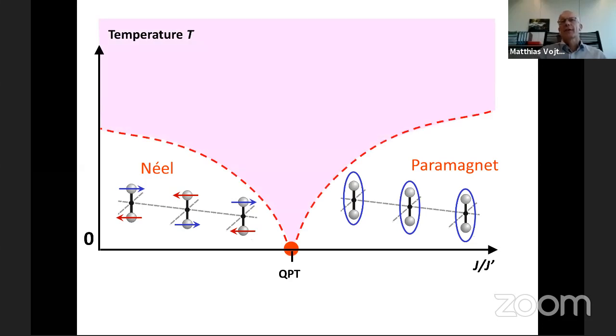And the resulting phase diagram, which you get from these considerations, looks like this. It looks like this because, for instance, the excitation energy on the right-hand side, which is needed to convert a singlet into a triplet, is large if you are deep in this paramagnetic phase, but in fact vanishes if you approach this quantum critical point, because this is the point where the system has an instability towards the other phase. Which means this dashed line is the crossover line where the density of excitations is small below the density of thermal excitations and large above the line.